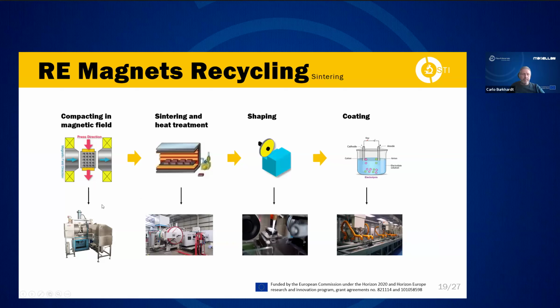Then what you do, if you have the powder, ideally you can take it, compact it in a field, sinter, heat treat it, shape it, and coat it, and it's just mirroring how you sinter magnets from virgin material. And that also makes it very simple to blend in recycled material into new material with the same processes. Should have probably added here the powder treatment. Powder treatment means jet milling. You have to jet mill the material. And during the jet mill, you can also take out impurities that haven't been filtered before with a sieving.